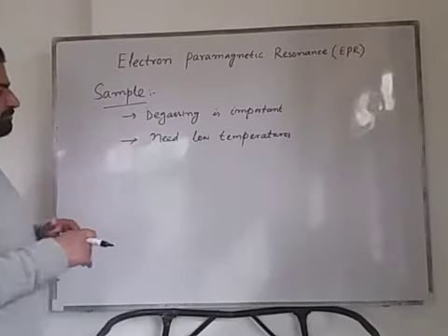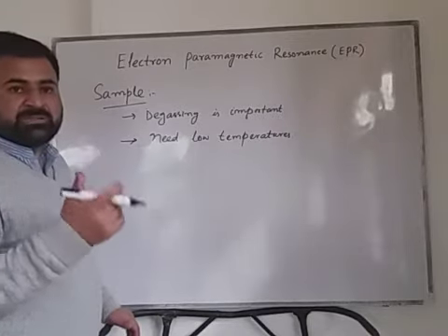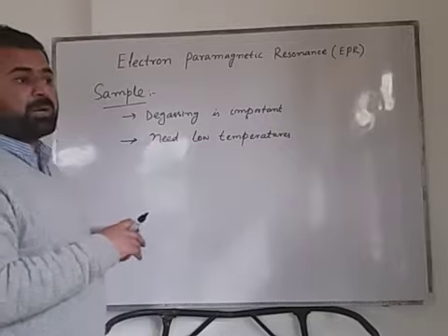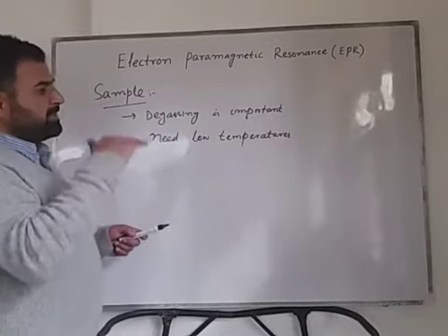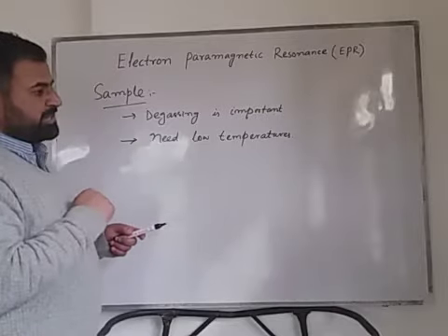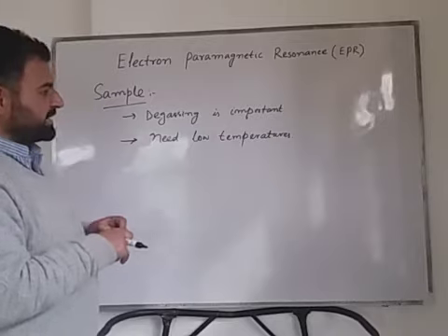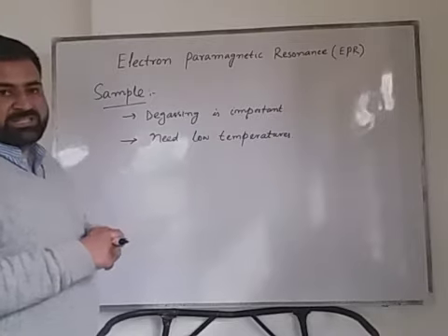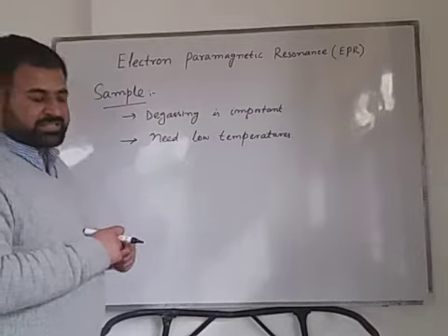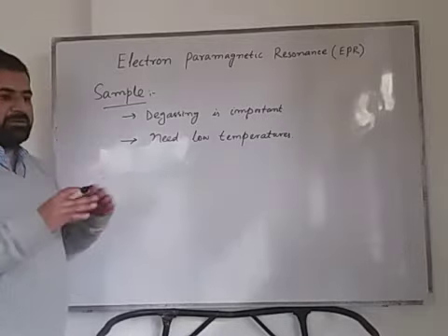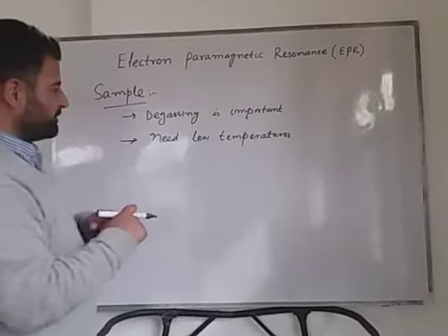That is because if you decrease the temperature gradually, there is a possibility of phase transitions in the crystal structure. That means the crystal may change into another crystalline phase, and that will give misleading results. So the cooling should be very abrupt so that there is no phase separation, and the same phase which we want to analyze remains.